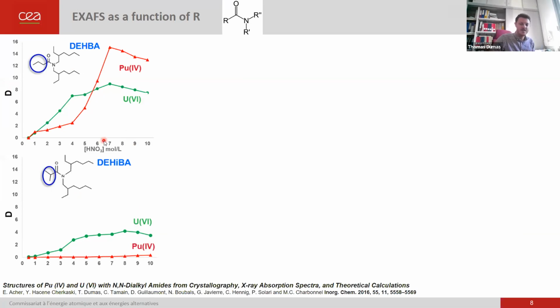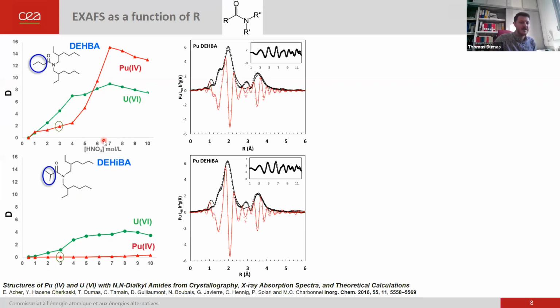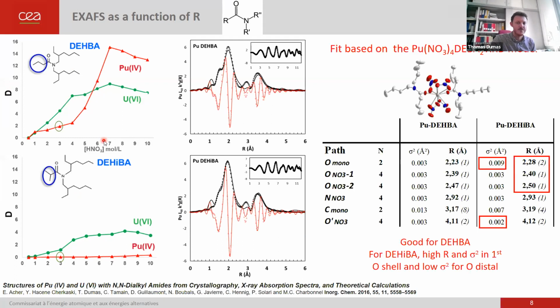And we wanted to understand what is going on in the organic phase. If you do an EXAFS spectra of it, you are going to find almost the same exact spectra. So it seems that you are extracting the same complex in the organic solution. And if you want to fit it, we have an XRD model of tetranitrate compounds with two extracting molecules in the first plutonium coordination sphere that works pretty well to fit the linear alkyl chain system. If you go to the branched alkyl chain system, you are going to fit it also, but you have kind of changing values compared to the XRD model that seems to be not completely perfect. Okay, and I will come back to that a bit later.